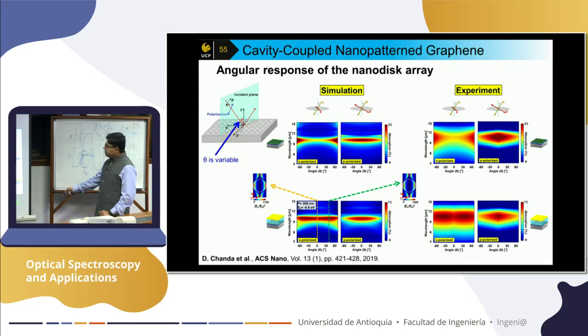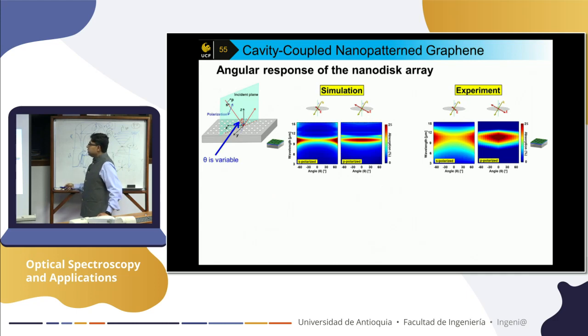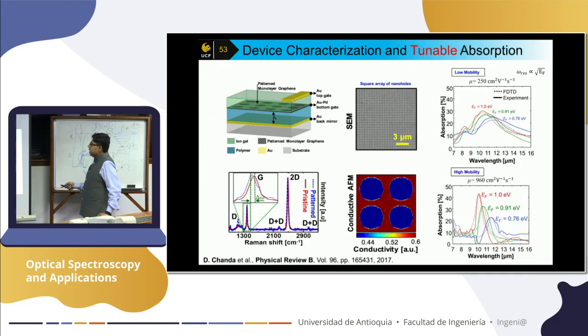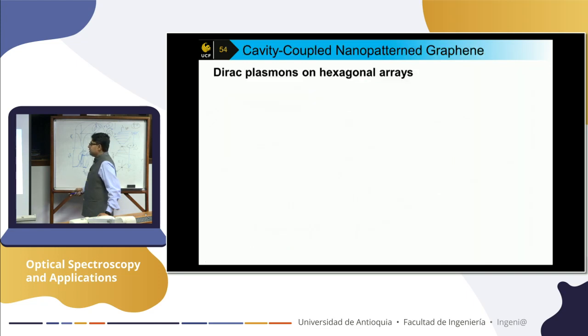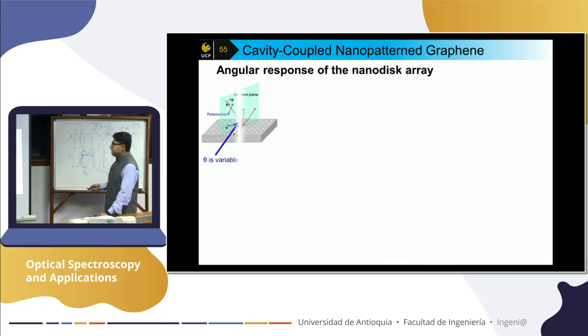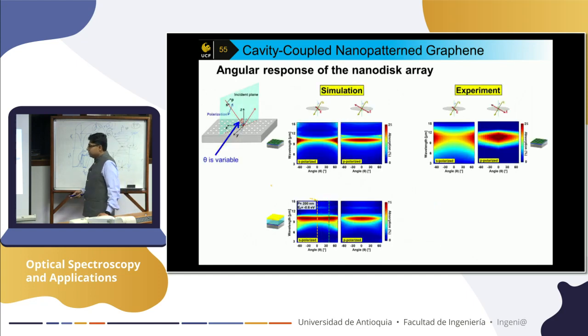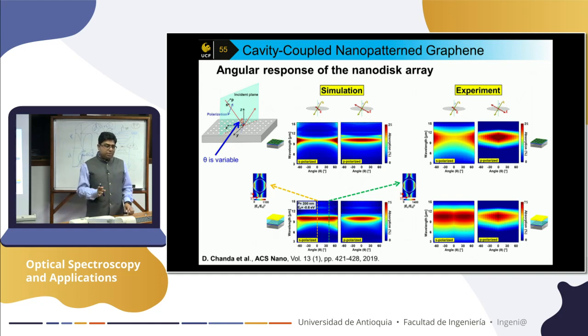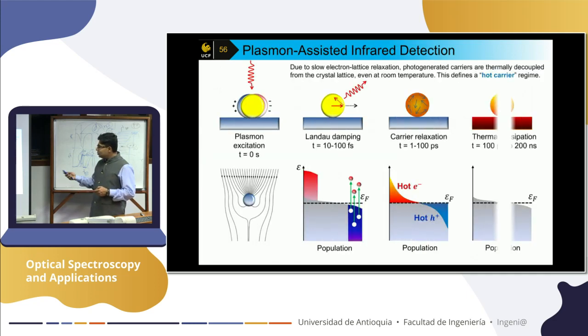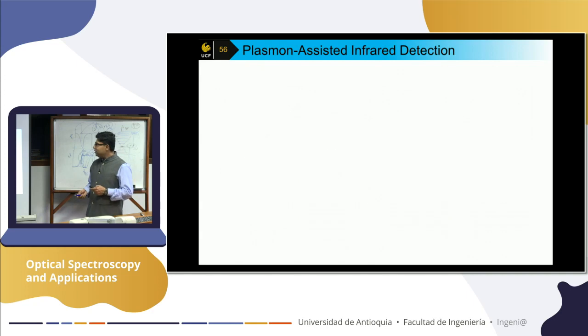So up to this point, the key take-home message: we could take a monolayer, 1 atom layer thick material, make it a high absorber, go from say 1% or 2% to about 60% absorption, and show that the absorption band can be dynamically tuned, enabling spectroscopic detection, and that the absorption is quite angle independent because of the design. Let's stop today, and tomorrow we'll go through Raman spectroscopy, time resolved pump probe spectroscopy, and end with the actual detection scheme, because it is a little convoluted to go through the physics and the mechanism, so we end with that tomorrow.